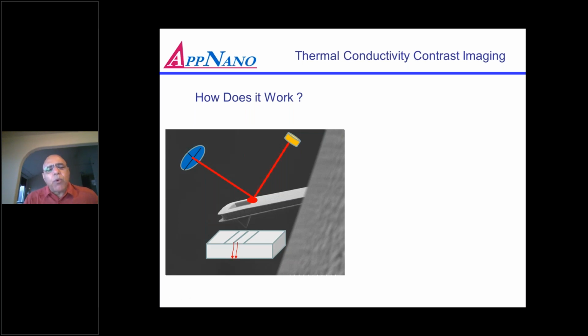So you have to have a compromise between the temperature change because of the heating and the sum signal you are getting. This is the laser, because we are splitting the laser into two halves. One is heating the thermocouple, and another is giving the sum signal for the laser feedback. So when you move it, in our module, you can see the temperature change displayed directly when you're moving the laser. So when you move the laser, this heats the thermocouple, and this temperature you can see in the module. So you can optimize where the maximum temperature comes, and then you can start doing the experiments.